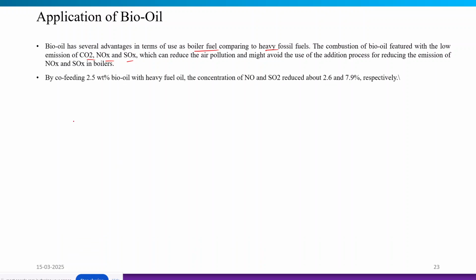So there has been a study that confirmed that co-feeding 2.5 wt% of the bio-oil with the fossil heavy fuel, the concentration of the SOx and NOx may be reduced by this percentage respectively. So there is a certain percentage of the co-feeding of the bio-oil with the already existing heavy fuel oil. So we can have reduced emission of the SOx NOx.